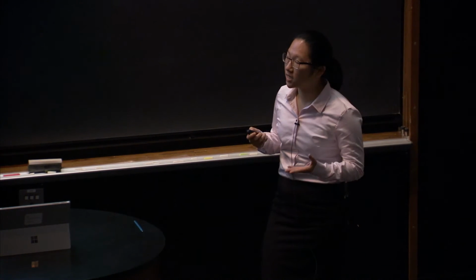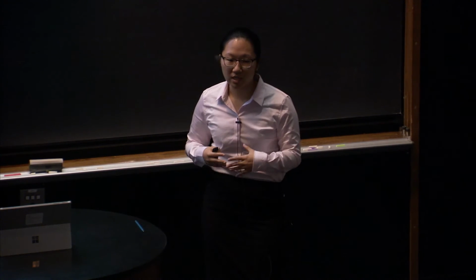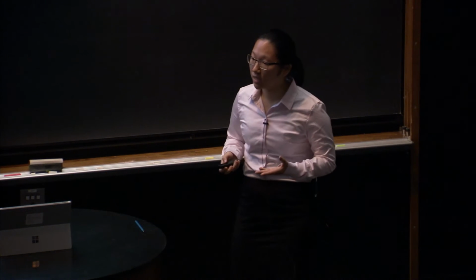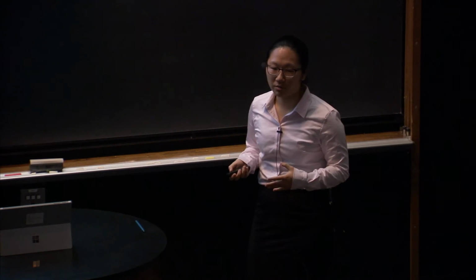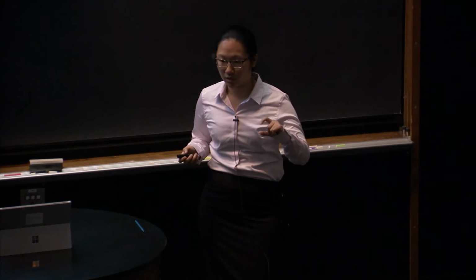The D peak is an indicator of the amount of disorder within the sample, or in this case, the number of edges that the graphene nanoribbons have. The G peak indicates the presence of sp2 hybridized carbon, which is graphene, and the 2D peak gives an indicator of how thick the layers are.